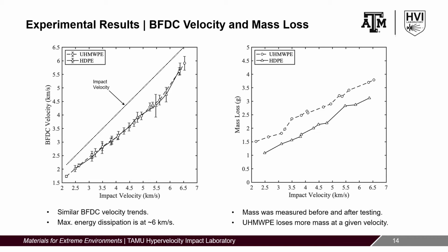When subjected to impact loadings consistent with those of hypervelocity impact, ultra-high molecular weight polyethylene's long polymer chains and higher degree of chain entanglement prohibit relative polymer chain motion that could occur at lower strain rates. As a result, the polymer chains break, and this breaking is exhibited macroscopically as fragmentation and fracture. In contrast, the shorter chain lengths and lower degree of chain entanglement in high-density polyethylene are more conducive to relative polymer chain motion, allowing for more larger-scale deformation, which results in less mass loss.